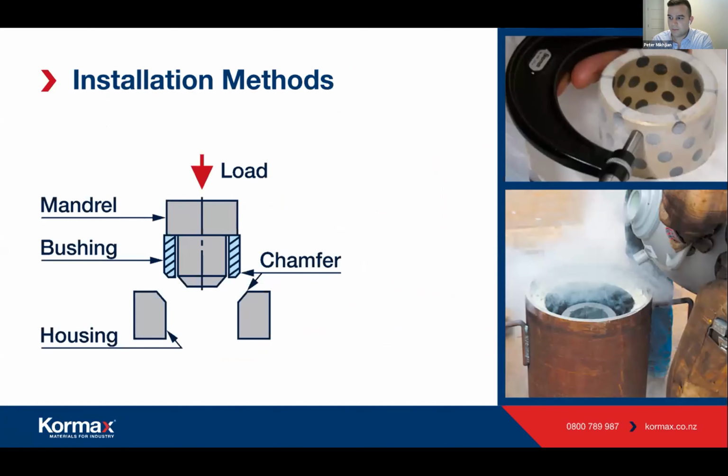Then for installation methods, there's two main methods for installing a bushing. We do either freeze fitting, where you're using dry ice or liquid nitrogen, or press fitting, and you're just literally pressing it into the housing. Both methods work great, and regardless of which method you'd use, you'd want to lubricate the housing to help with the install, and then you want to apply a break-in lubricant between the shaft and then the bushing ID.